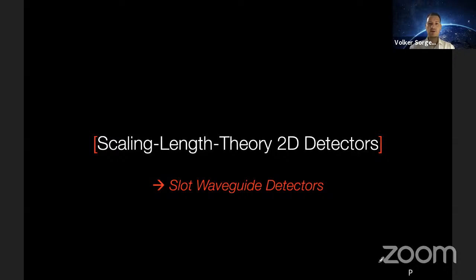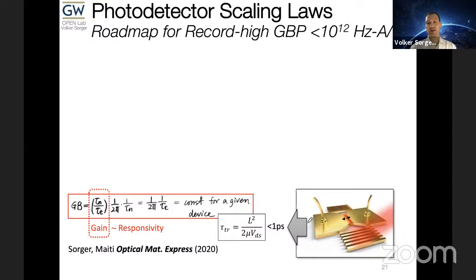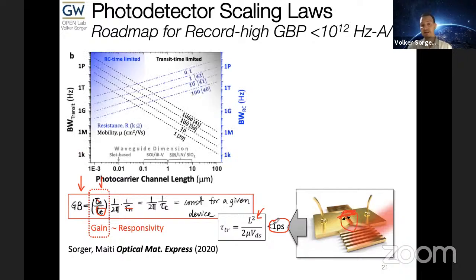And then lastly, talking about scaling length theory. We're borrowing the idea from field effect transistors to build very efficient opto-electronic devices, in particular detectors. The gain bandwidth product is given by the gain. This is the carrier lifetime over the transit time, divided by the carrier lifetime. You notice the carrier lifetime cancels, so you're left with the transit time. Transit time is the time an electron takes to be collected by your source and drain contacts. If you make your length, this L, very, very short, on the order of tens of nanometers, like a plasmonic slot, now your transit time can be a picosecond, which would be approaching a terahertz.